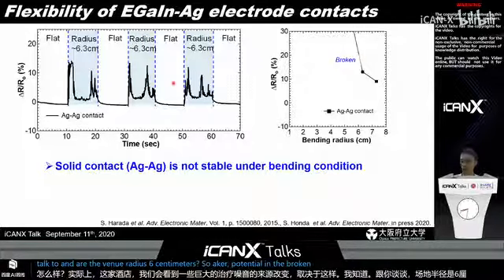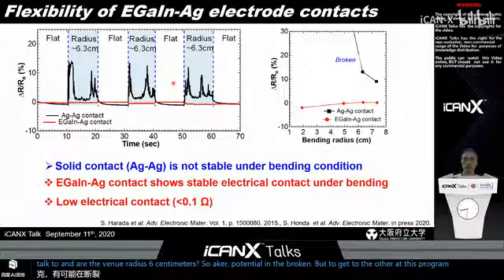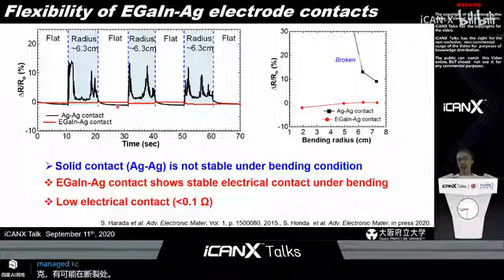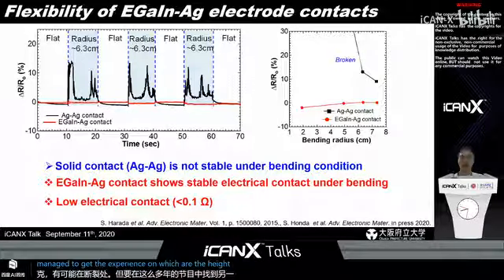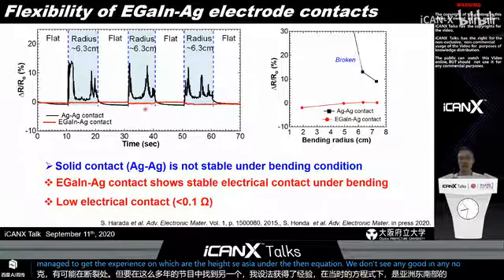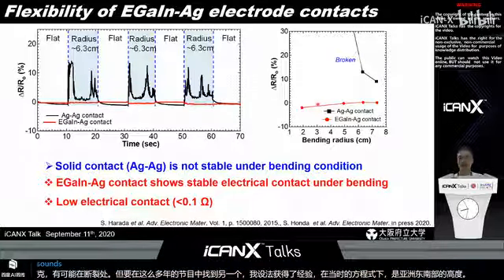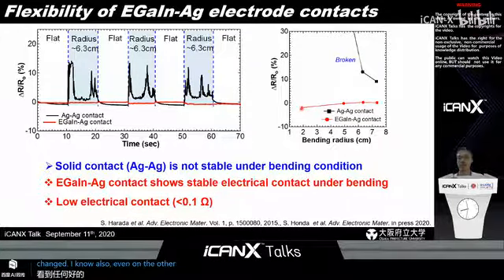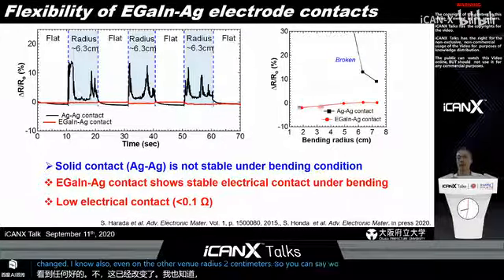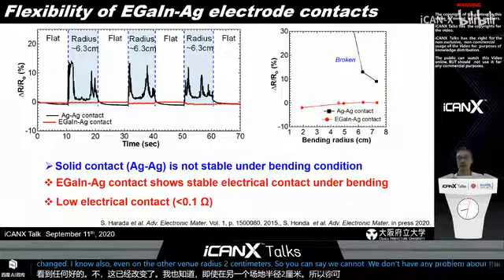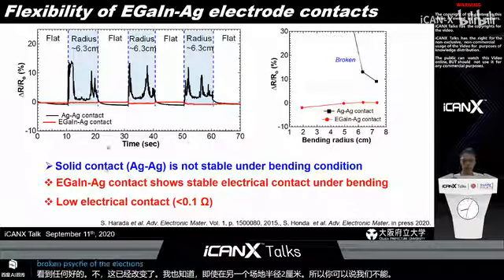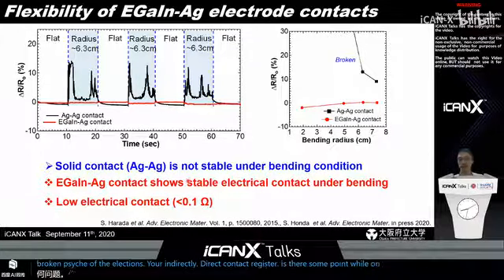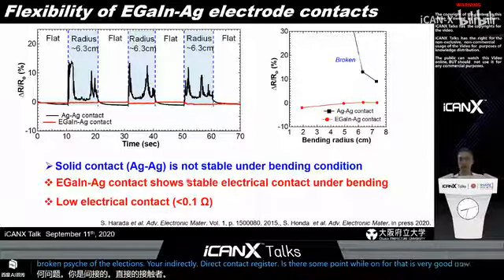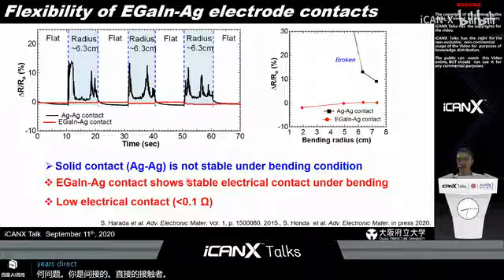So to address this problem, we use the liquid metal. As I explained, due to the high surface tension, even under the bending condition, we don't see any large resistance change. And even under a bending radius of 2 centimeters, we don't have any problem of broken circuit connections. Using that technique, the contact resistance is less than 0.1 ohm. That is probably good enough to use as an electrical connector.